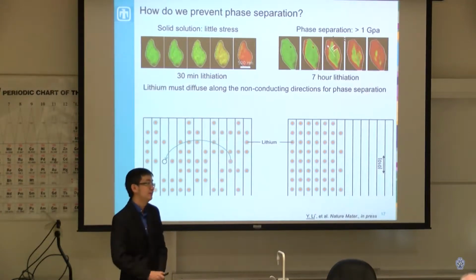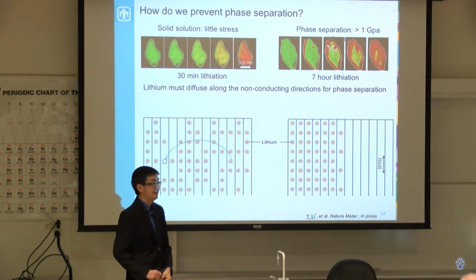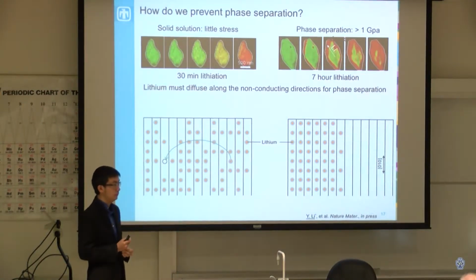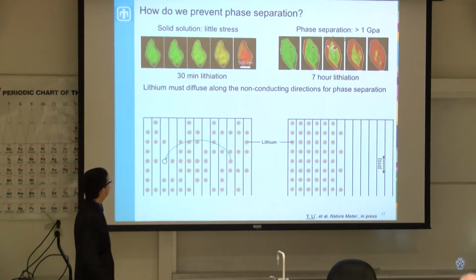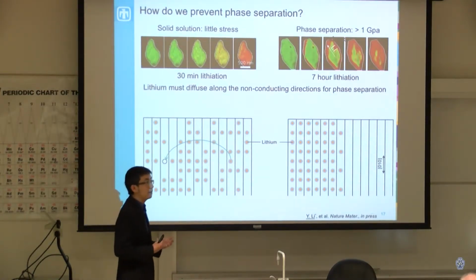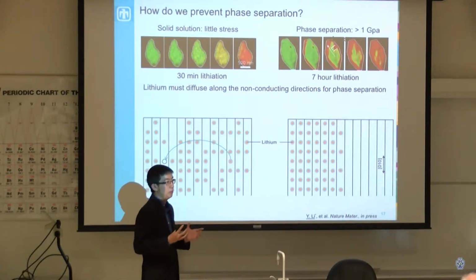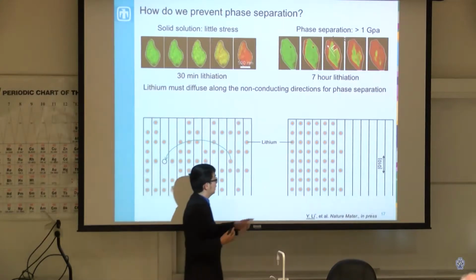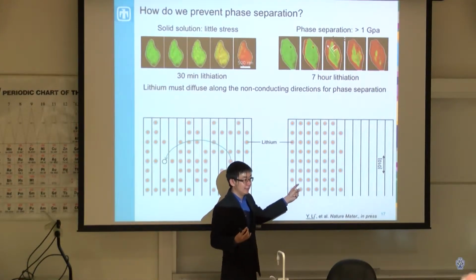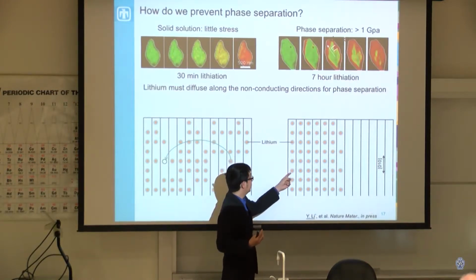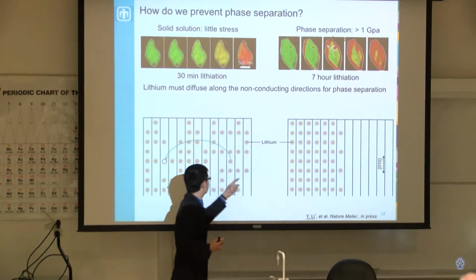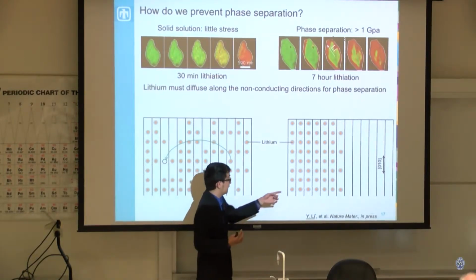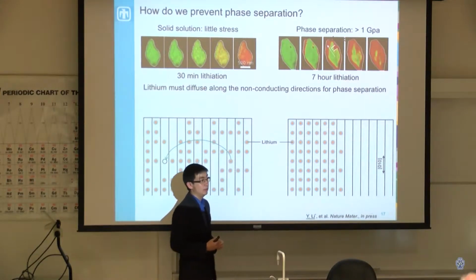Yes? Dr. Li, I think I personally need one piece of information. Maybe you said it, but the efficiency is coming from the less stress, and is that because you mechanically break apart these lithiation sites and you have smaller crystals, and that's less efficient? The reason that lithium likes to be near other lithium is that when you put the lithium in, it distorts the bonding environment such that it's easier for lithium to be next to a region that already has lithium in it. If you think about a lithium in this environment versus a lithium in this environment, the bonding of the crystal makes it so that lithium prefers an environment like this.